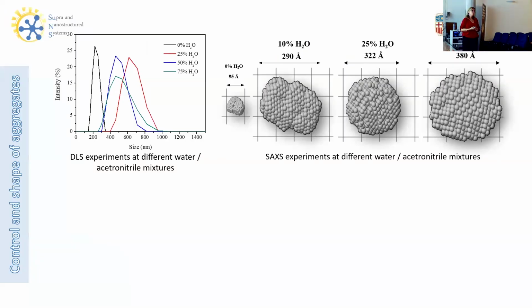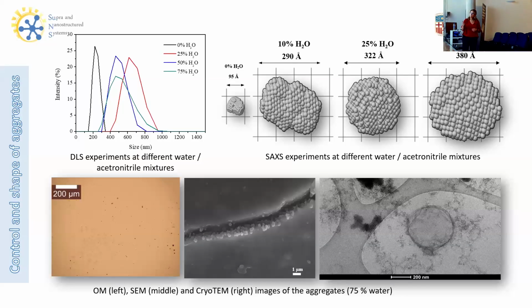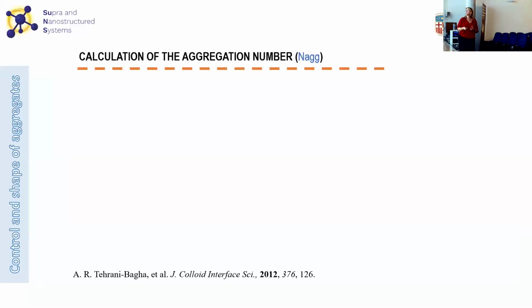And we required other techniques, for example, DLS, dynamic light scattering, that verifies also the presence of some spherical aggregates. And also we went to the synchrotron and we could perform some small angle X-ray scattering, that both confirm the formation of these spherical aggregates. This was also confirmed by microscopy. So obviously microscopy is very nice to really know what is the shape of our samples. So both by optical scanning electron microscopy, but also by cryo-TEM, this indicates that in solution we still have these self-assembled spherical structures. Okay, so we could characterize through a wide variety of different techniques the formation of our aggregates, their supramolecular assemblies, their shape and size.